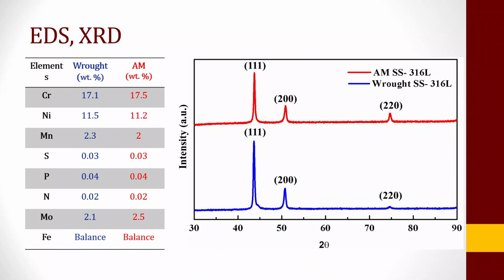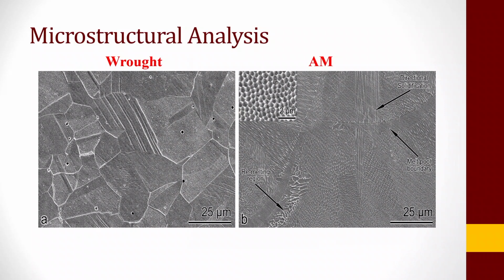The first thing we do is quickly perform the EDS analysis to see if the compositions of the wrought and additively manufactured samples are the same or not. You could see in the table on the left that the additively manufactured and the wrought are pretty much the same in composition. Similarly, when you look at the XRD graph, you could also see that the XRD patterns are pretty much the same for both of the stainless steels.